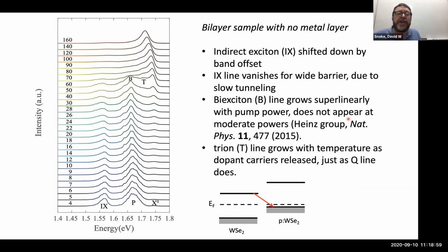Okay, why is the indirect exciton shifted so far away in energy? So this is a different set of data. This is a bilayer sample with no metal. First of all, in all these bilayer samples, when I have a doped and an undoped junction in equilibrium, there's going to be a band offset because the Fermi levels line up. And so the spatially indirect emission is going to have much lower energy. And that's been well documented in a number of papers showing the indirect exciton. It's way down here in energy.